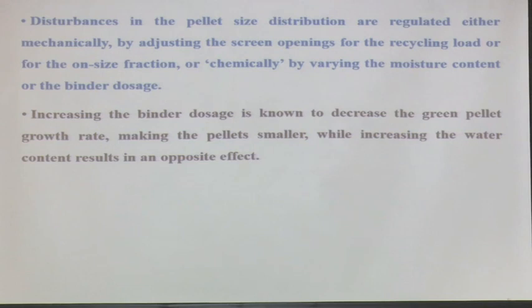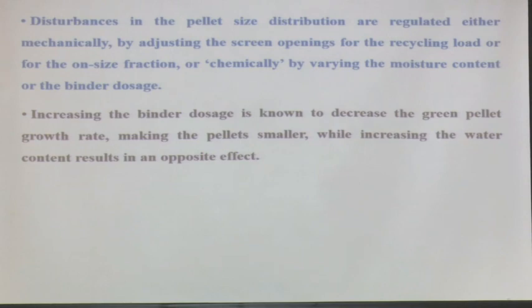Increasing the binder doses decreases the green pellet growth rate, making pellets smaller, while increasing water content has the opposite effect. There is a critical amount of water needed — the optimum — above which the particles start getting dispersed; that is called flooding. How much binder is needed — whether water or other materials — is dependent on the material's surface characteristics.